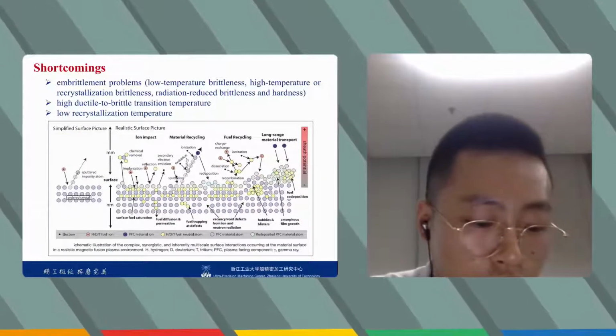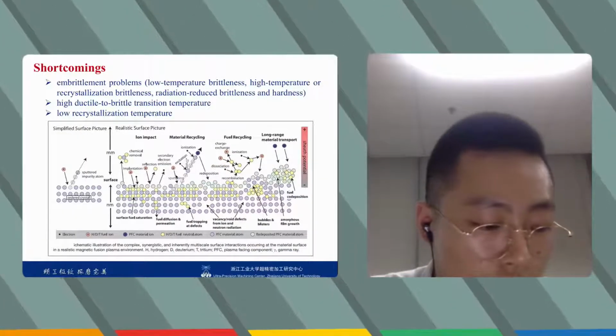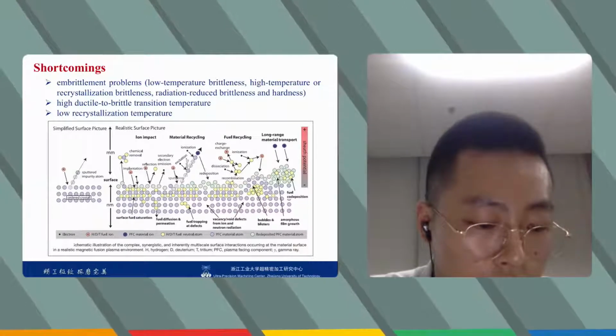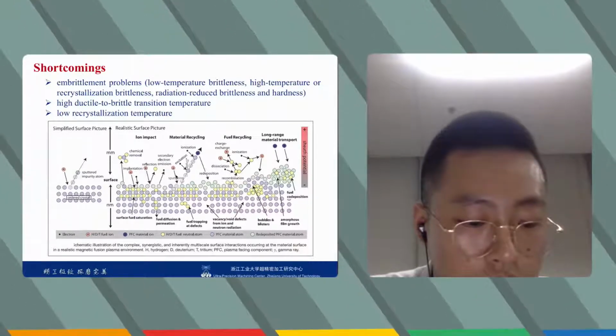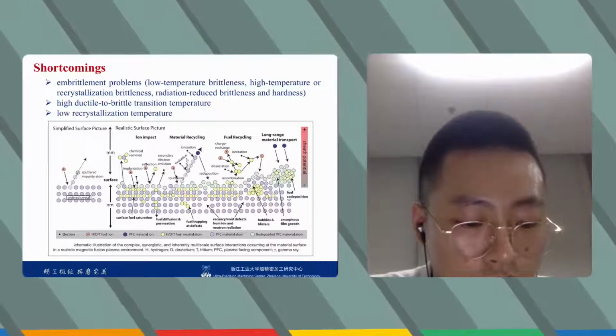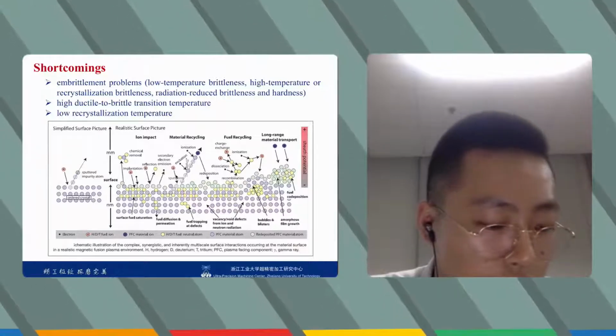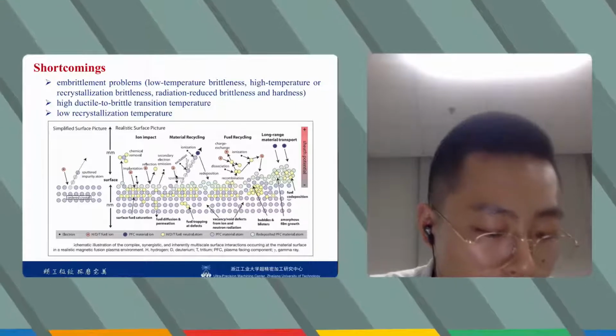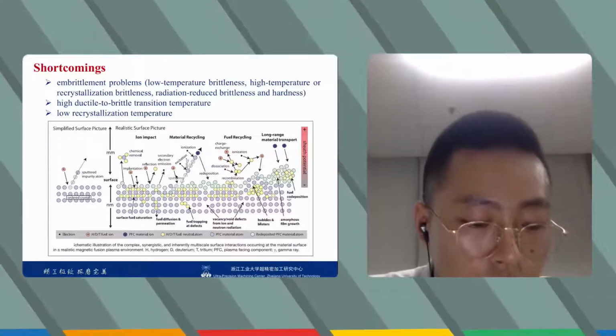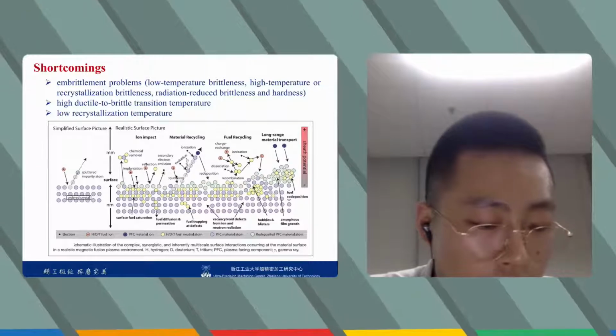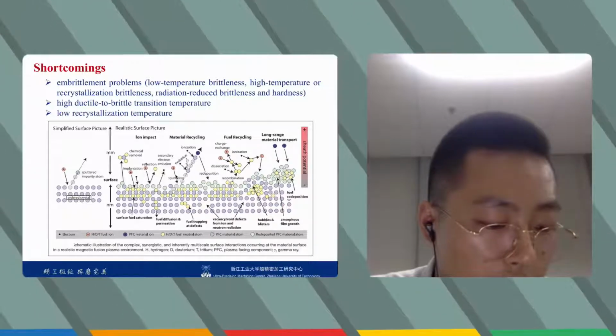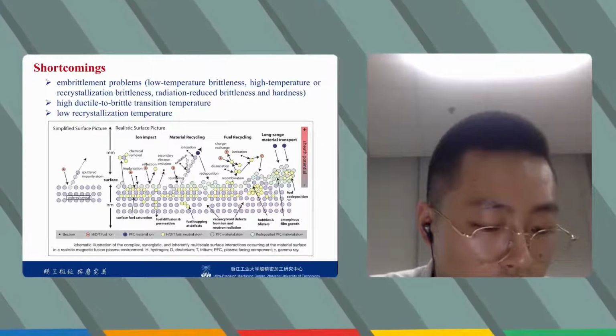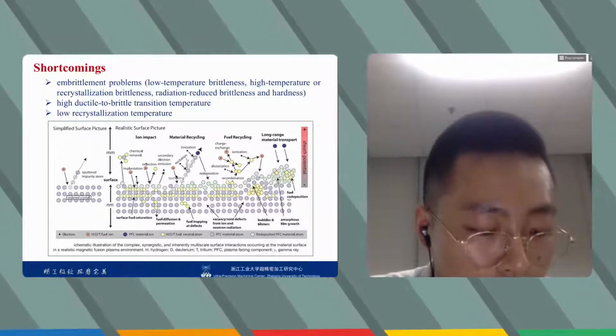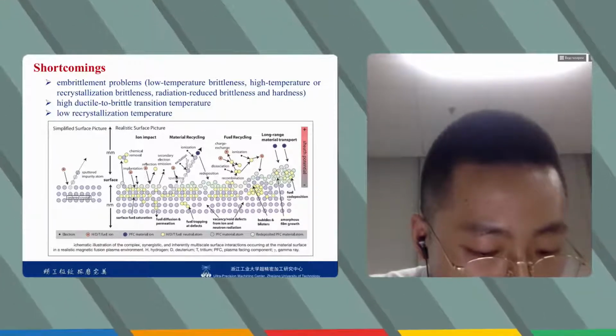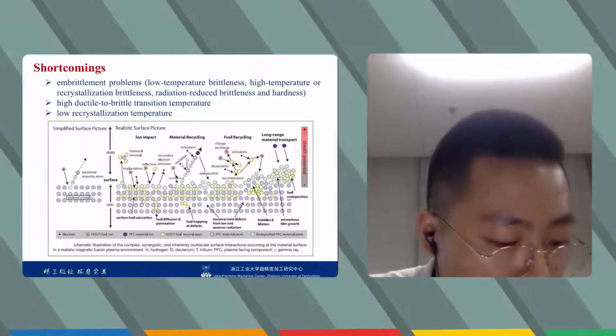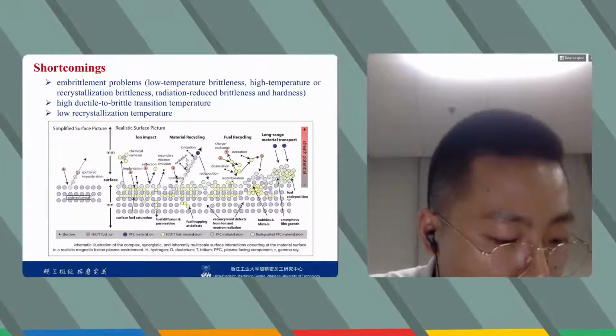However, some shortcomings of tungsten have a negative influence on its application, such as serious embrittlement problems, a high ductile-to-brittle transition temperature, and low recrystallization temperature in the reactor environment. Plasma-facing materials have to bear high thermal load, high helium plasma flux, and high energy neutron irradiation.